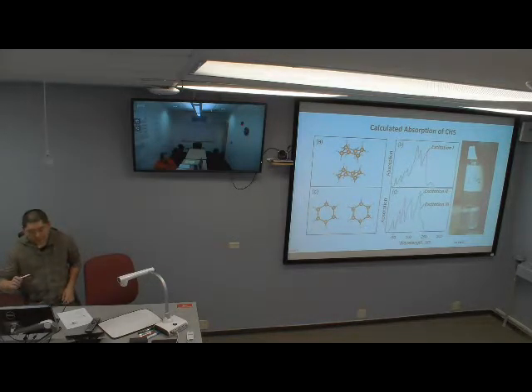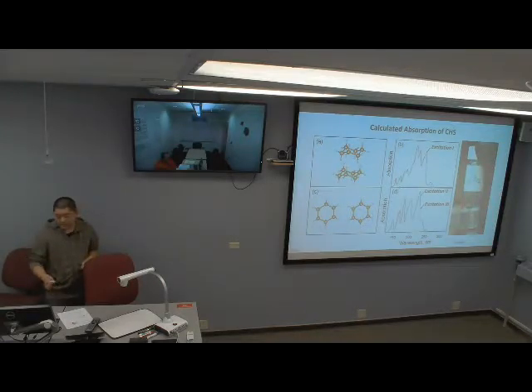This time, our simulation cell consists of two CHS molecules, and we consider two placement configurations, face to face and side by side. And we compute the absorption spectrum for both of them. And here is the result. We found there is no absorption in the visible range. This picture shows the liquid cyclohexasilane, and we can see it is transparent. So this means our calculation is in qualitative agreement with experimental data in terms of absorption.